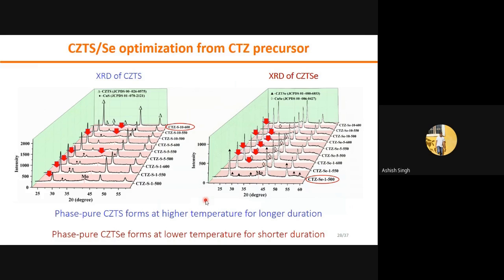First, we tried to make phase pure CZTS and CZTSe on Mo-coated glass, and this is the XRD pattern of the same sample. At different temperatures we annealed the metal precursor in a sulfur atmosphere, and at different temperatures in a selenium atmosphere. In this condition, the red highlighted arrow indicates the impurity phase in the system. From these XRD patterns, we found phase pure CZTS forms at higher temperature for longer duration, while phase pure CZTSe forms at lower temperature for shorter duration, in 1 minute at 500 degrees Celsius.